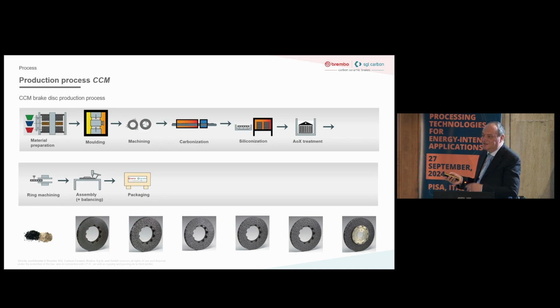We have already seen this several times today. Material preparation means chopped fiber and phenolic resin, thermoset. So we fill the mold with it. It's not so trivial, because if you have, for example, 60% of volume here, 40% there, the ratio is not 60-40 of the weight, but the target is to obtain the same density. Why is it not the same? Because there is the flow of the material in the different areas. We are pressing from the top and not from the bottom. We are heating in a different way. So it's not so easy, and we have to control it.